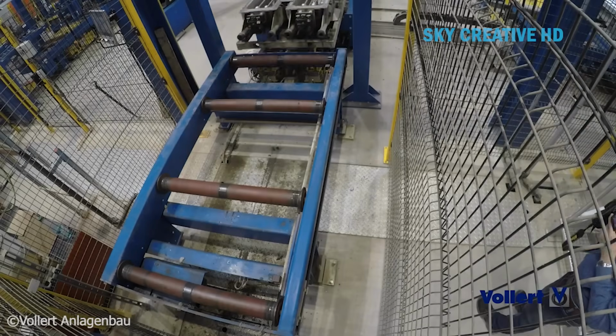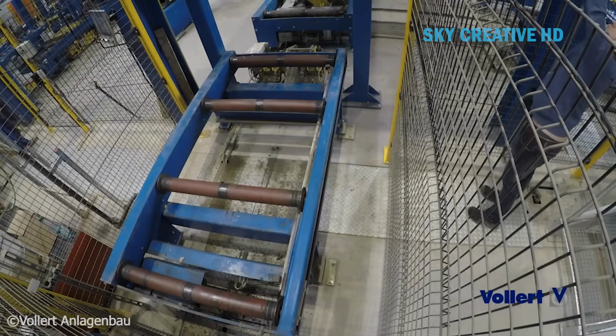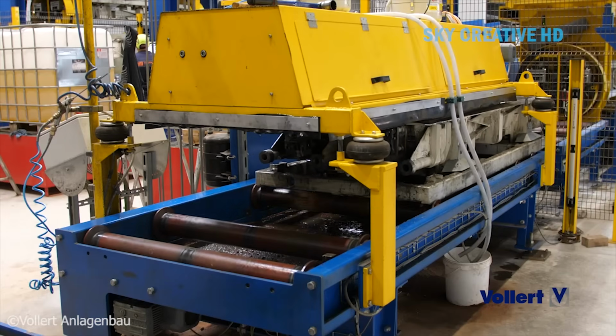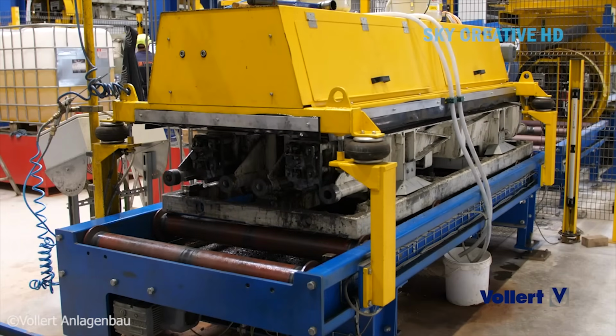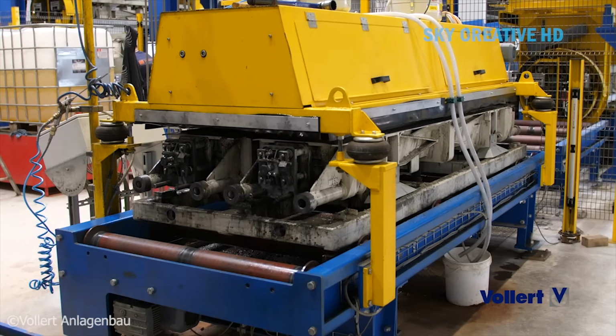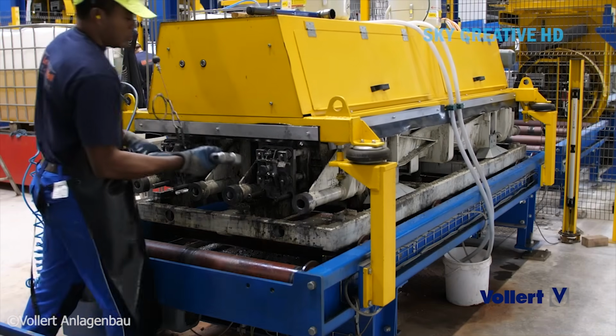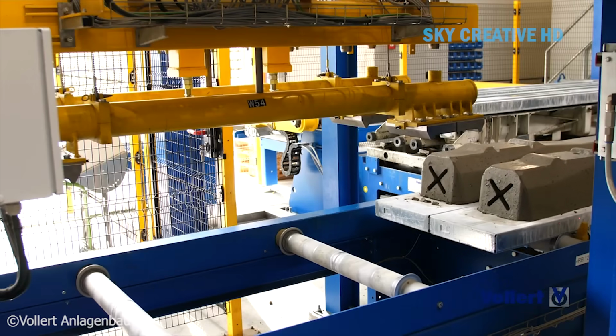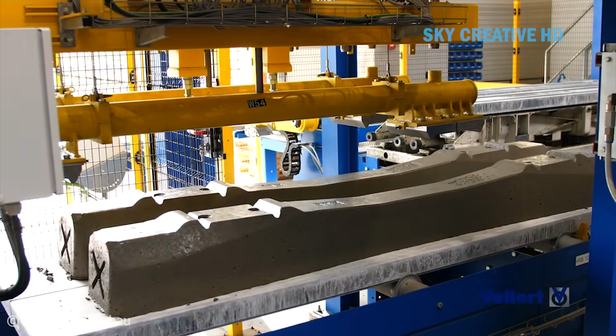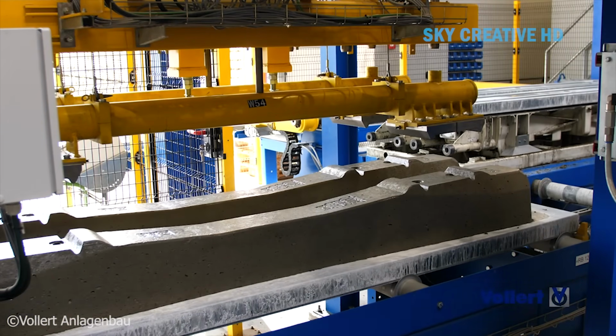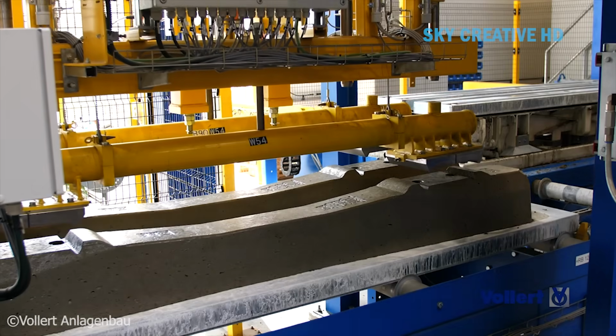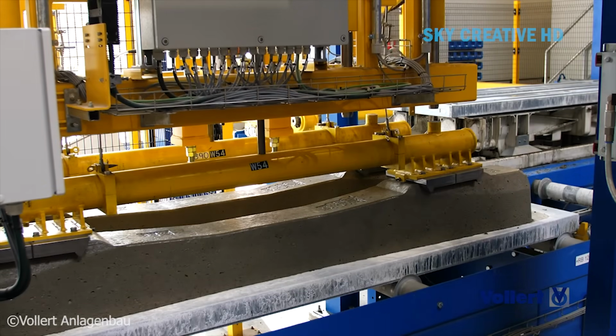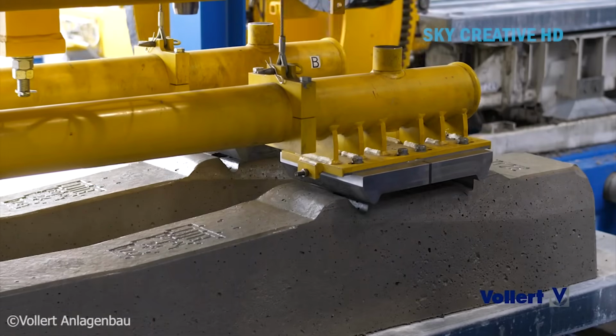Too little mixing and the concrete won't achieve uniform strength. Too much, and you'll introduce unwanted air bubbles. Now comes the heart of the operation, the pre-stressing system. Before the concrete is even poured, high-tensile steel wires are stretched along the length of the forming bed under precisely controlled tension, typically around 28,000 pounds per square inch. This pre-stressing technique, pioneered in Europe in the 1940s, is what gives these ties their incredible durability and resistance to cracking.